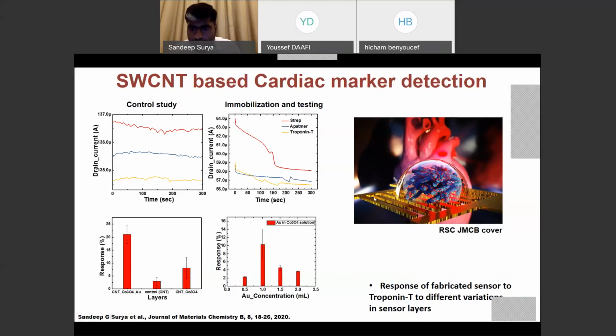So you have the nanorods deposited over here on top of single wall carbon nanotubes, and then the bubbling that you see around here is what happens when you do the process of immobilization. Initially, we have put streptavidin to form a very good binding, and then on top, after 5 minutes, we have drop casted the concerned DNA aptamer that is related to troponin T on top of the streptavidin. This is the primary receptor or binding element that is required.